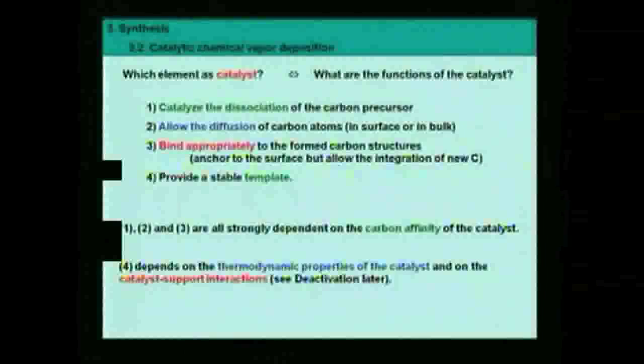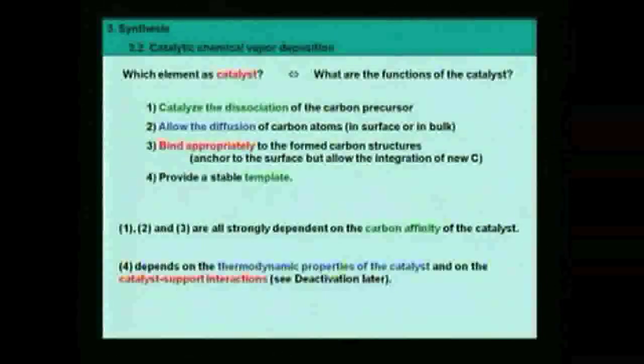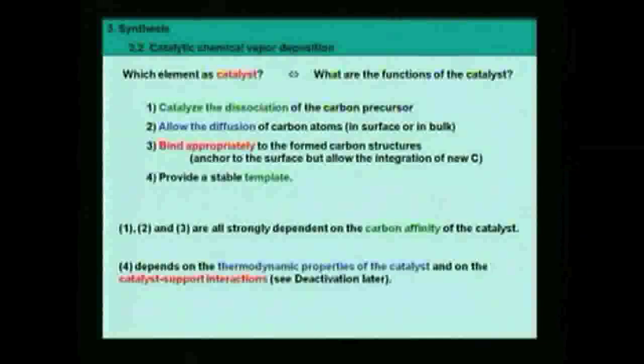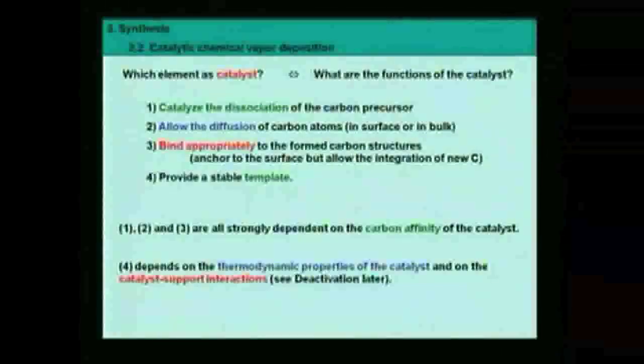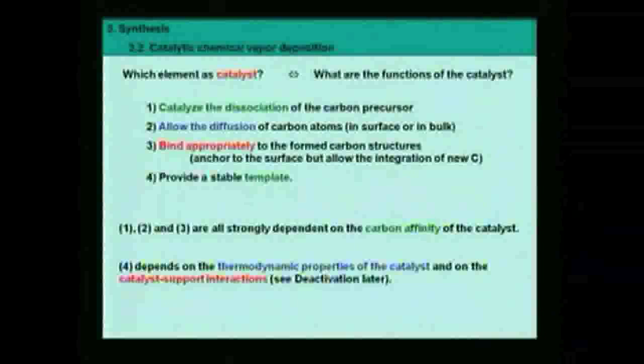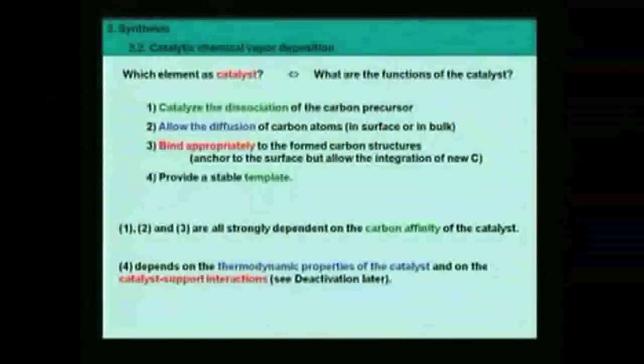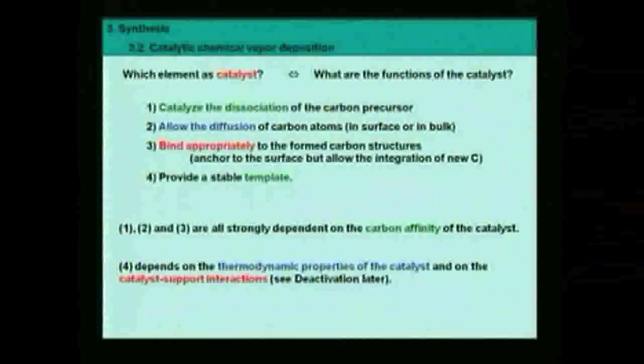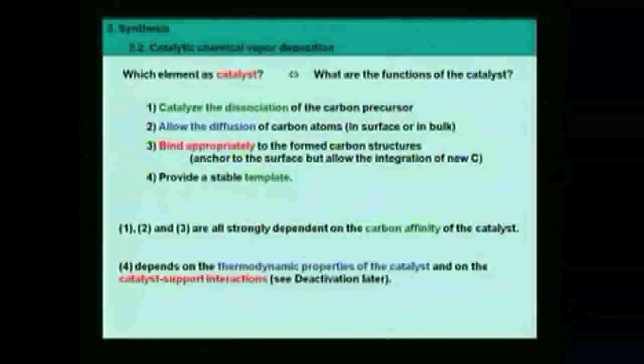And the carbon affinity is important also for an appropriate binding between the carbon structure and the surface of the catalyst. Concerning the last point, point 4, this mainly depends on the thermodynamic properties of the catalyst itself, like its melting point, like its sublimation point, like its wetting properties, its surface tension, and also this wetting not only depends on the catalyst itself, but also on its interactions with the support.